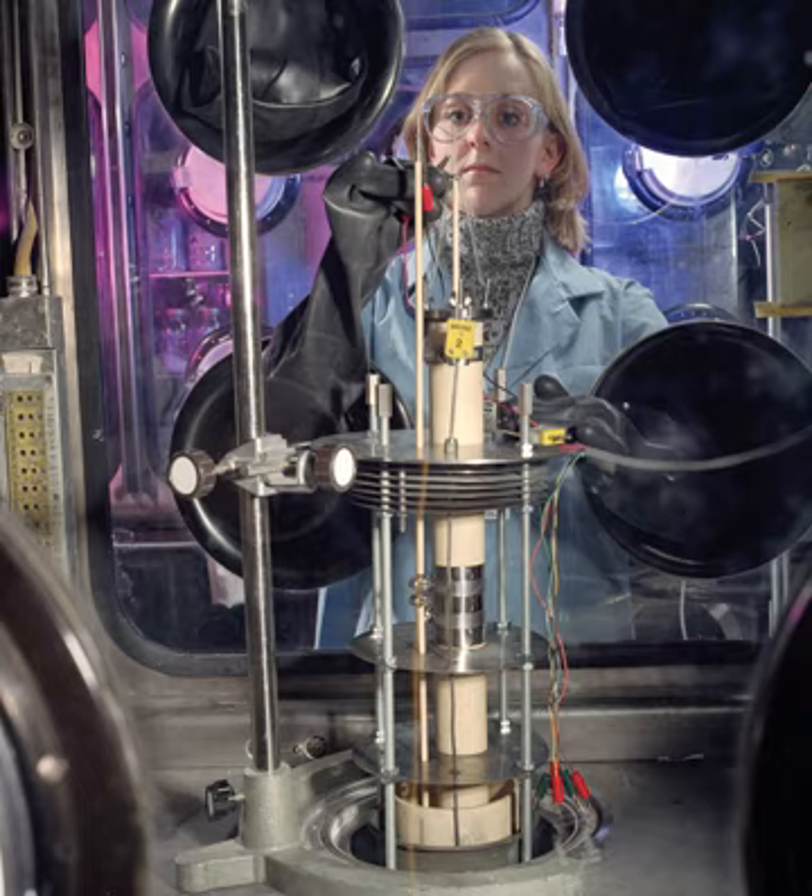The wanted metal can be isolated using a molten alloy of an electropositive metal and a less reactive metal. Since the majority of the long-term radioactivity and volume of spent fuel comes from actinides, removing the actinides produces waste that is more compact and not nearly as dangerous over the long term. The radioactivity of this waste will then drop to the level of naturally occurring minerals within a few hundred, rather than thousands of, years. The mixed actinides produced by pyrometallic processing can be used again as nuclear fuel, as they are virtually all either fissile or fertile, though many would require a fast breeder reactor in order to be burned efficiently.